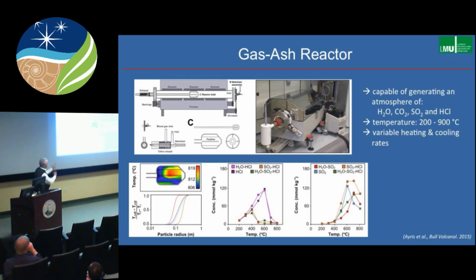It's basically a tumbler, which is a classic way to react any powder with gases to ensure that there's a reproducibility of exposure of fresh gas ash surfaces to the gas which is flowing through along the axis of the device. And this is the actual beast. There it is in the lab. Sits in a fume hood because we put nasty gas mixtures into this, a lot of them containing sulfur.